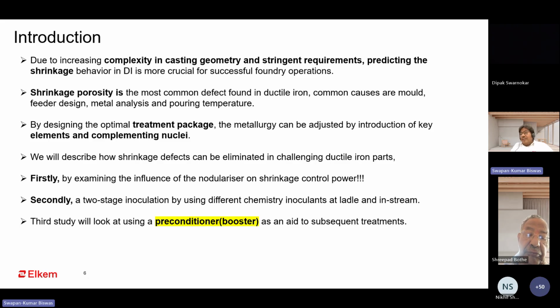Due to the complexity of casting geometry and stringent requirements, predicting the shrinkage behavior in ductile iron is crucial for successful foundry operation. Shrinkage is the most common defect in both gray and ductile iron, but identification is most important. Normally, most foundries study a few defects, slag or sand related defects, and gas or blowholes, but very rarely do they check the microstructure to find out the type of defect: shrinkage, gas related, or nitrogen in the case of gray iron. So it is very important to identify the defect, then you can take corrective action.